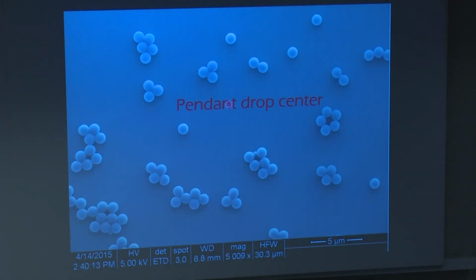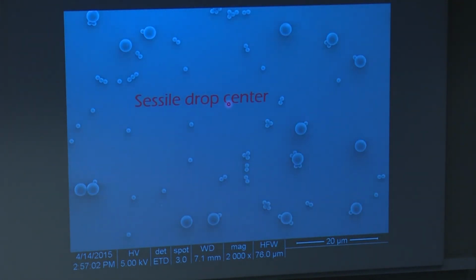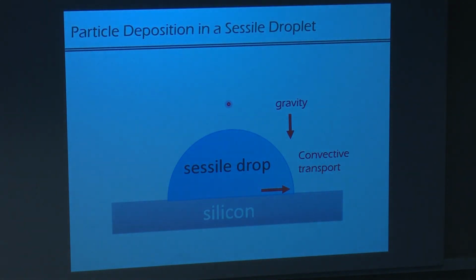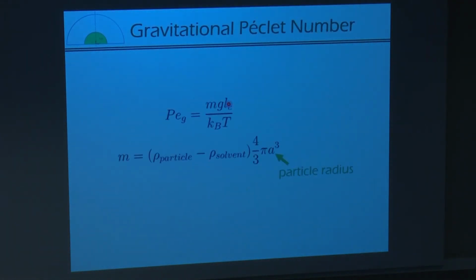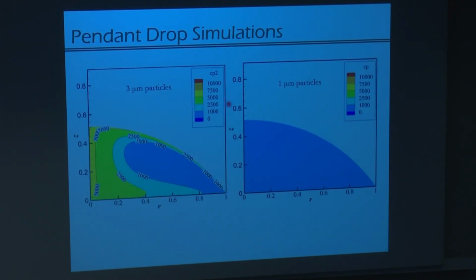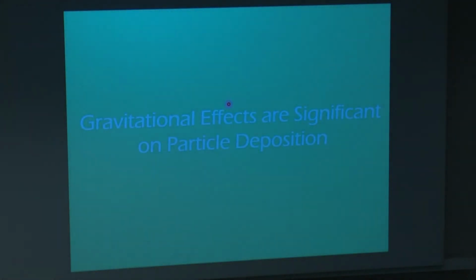You get big particles in the center. Sessile drop, you get big and small particles in the center. And so when you model this, you have to include the gravitational Péclet number. And finally, when you do the simulation, it shows that you get big particles in the center and virtually no small particles in the center.